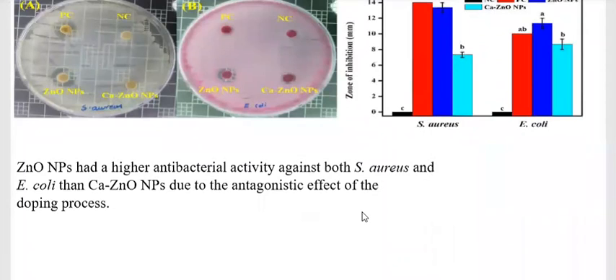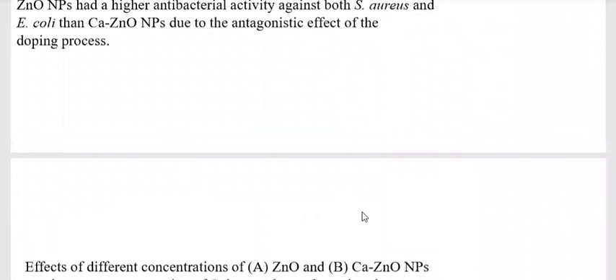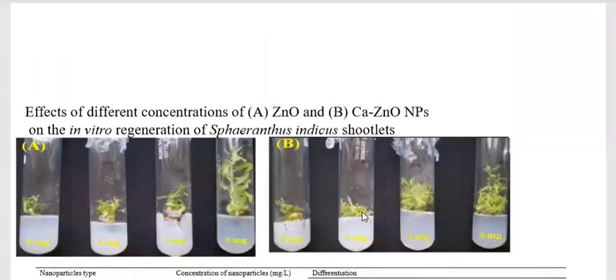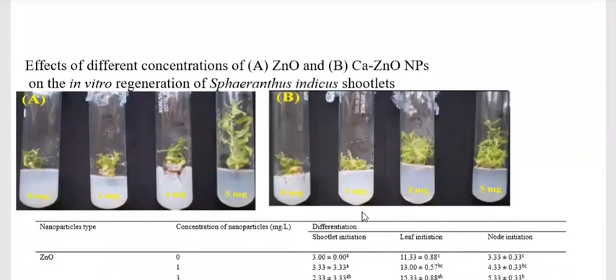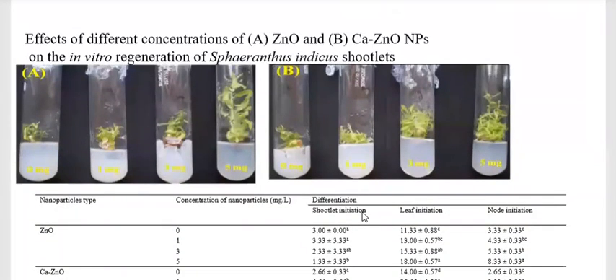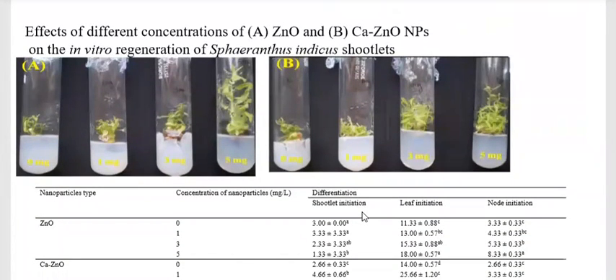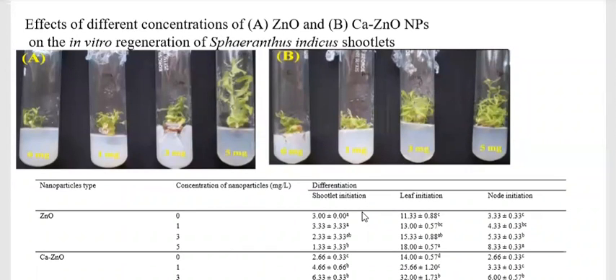Another application is with different concentrations of zinc oxide and calcium doped zinc oxide nanoparticles. The Gloriosa explants were inoculated in MS media incorporating the different concentrations of zinc oxide and calcium doped zinc oxide, which gradually increased shoot initiation, leaf initiation and node elongation as compared to pure zinc oxide nanoparticles. The calcium doped zinc oxide nanoparticles, as a bimetal oxide nutrient, enhance shoot initiation as well as leaf initiation and node elongation. Zinc oxide and calcium doped zinc oxide have a hexagonal structure by X-ray diffraction.